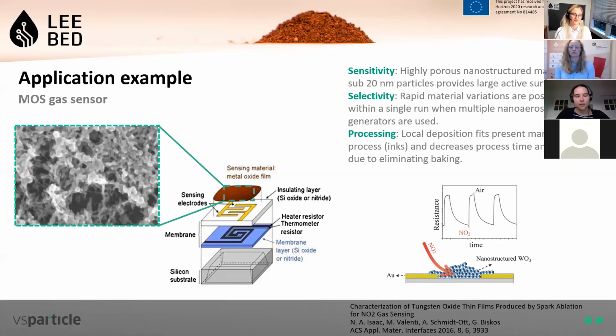And so this showcases that these printed layers provide excellent sensitivity due to their highly porous nanostructured morphology, and due to the really small particles, the sub-20 nm primary particles, that provide a large active surface area for the gas to adhere on. You can scan the various materials to optimize the selectivity, as when you use two generators, you can rapidly vary the material ratio, and so run a scan to see what works best for the desired analyte gas.